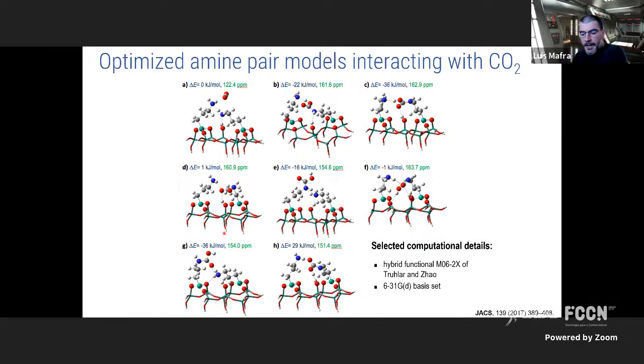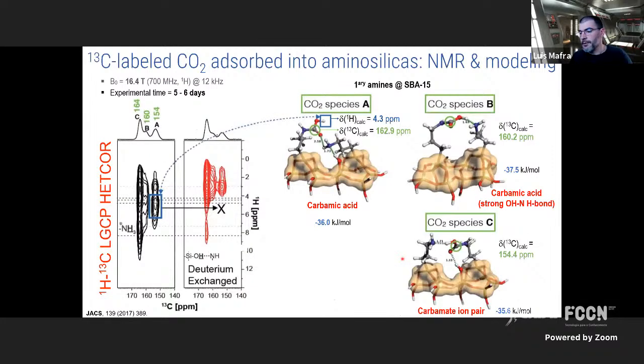Of course, to avoid far-fetched assignments, we need to couple our experimental data with computational analysis. So we have done several cluster calculations where we have a silica slab, where we optimize the distance between two amines. We have made maximum loading possible, so we assume that the amines are in pairs for these models. We have also done isolated amines, of course, but I will not go into all these details. This is the level of theory we have used for our calculations. And we have done probably hundreds of calculations, okay? So I will skip it.